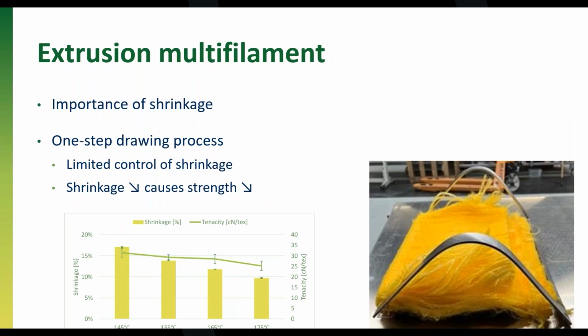As mentioned, we have limited control in this one-step drawing process over the shrinkage. We can decrease the shrinkage a little bit with the relaxation at the last roll, but we also see that we decrease the strength by that. So going from 35 centinewton per tex to only 25, which is a large decrease, but we can achieve also a decrease in shrinkage to just below 10%, of around 10%. So also quite a large decrease in shrinkage, but also the mechanical properties are suffering, which is not ideal for the resulting properties of the composite materials.